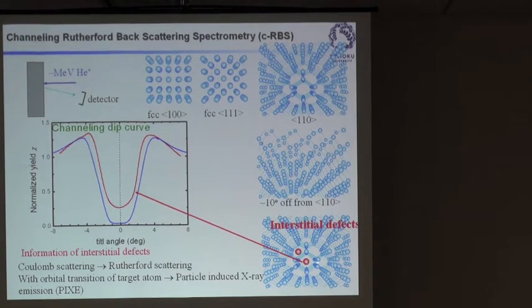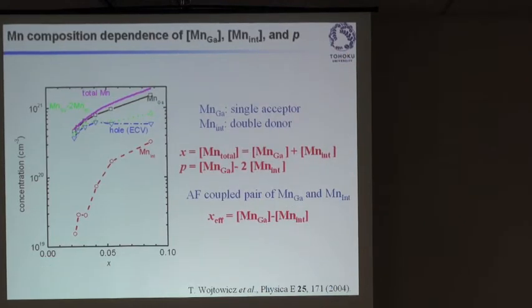And this manganese is highly mobile, and when oxidized at the surface, the bare manganese concentration at the surface is reduced. So there's always a diffusion going on from bulk gallium manganese arsenide towards the surface. So that's the reason why we have seen a very large annealing effect at low temperature. So this is a summary slide, which I will just go through with you.